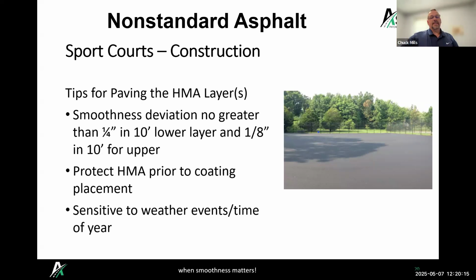Some more tips for paving the asphalt: smoothness deviation, because those slopes and grades are so important, no greater than 1/4 inch in 10 feet on the lower layers, and no greater than 1/8 of an inch in 10 feet on the upper layers. So very tight tolerances there when we're paving. So we need a lot of controls, to make sure that we're putting things in at the proper elevations.